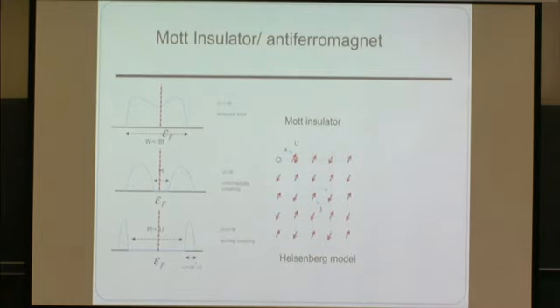And if you dope this system, say by taking an electron out, then you have a hole here. The hole starts to move, and it will carry charge, and the chemical potential moves to the lower Hubbard band. And many people believe that the realistic case for cuprates is probably some intermediate U.